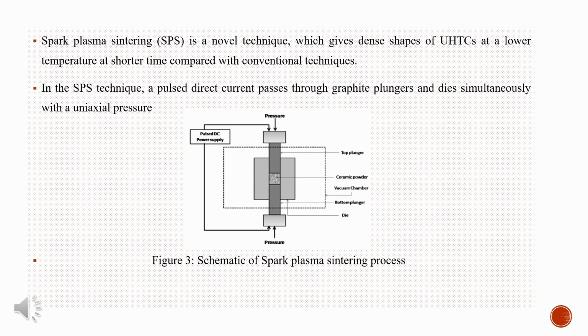Spark plasma sintering, SPS, is a novel technique, which gives dense shapes of UHTCs at a lower temperature and shorter time compared with conventional techniques. In the SPS technique, a pulsed direct current passes through graphite plungers and dies simultaneously with a uniaxial pressure. Figure 3 shows the schematic diagram of spark plasma sintering process.